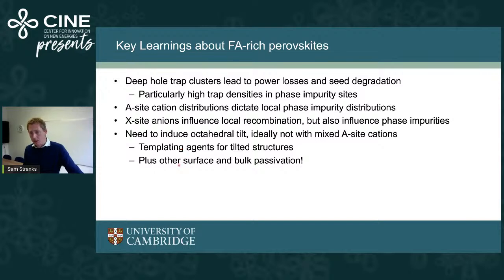But it also means we still need other passivation to reduce overall defect densities, because in the end, they will fundamentally seed degradation and also trapping. So it's important to not just stabilize the phase of the material, but also to address any remaining defects that are there, even in a very good film.